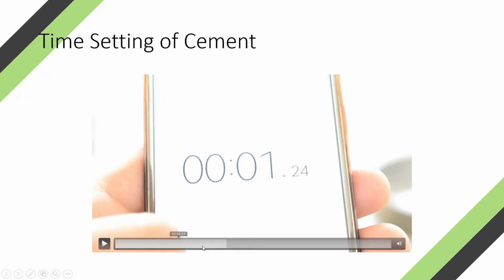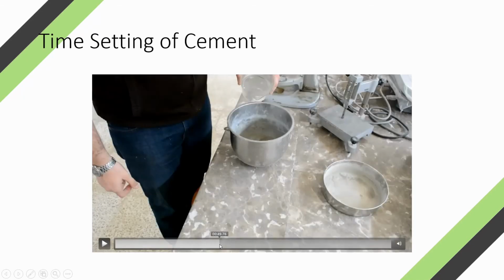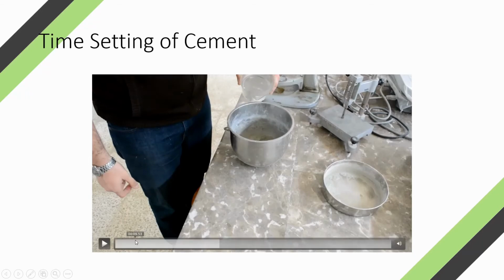So, ito nga pala, yung amount of water na ilalagay ninyo is yung amount ng water at normal consistency ng cement. Kapag nakuha nyo na yung normal consistency ng cement nyo, kung gaano karami yung amount ng tubig na yun yung gagamitin nyo rin for setting time of cement. So, hindi kung ano-anong amount ng water yung ilalagay dito. So, unang itetest dapat is normal consistency of cement.